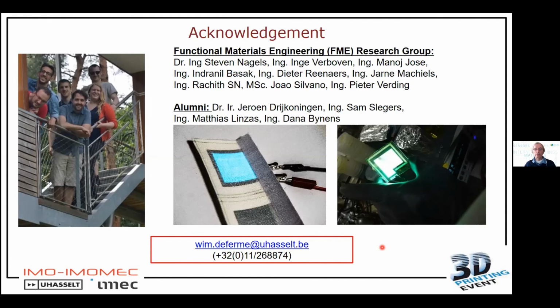Well, let's say that we have a few companies that have a lot of interest in this ultrasonic spray coating for roughness reduction and adding functionalities to 3D printed parts. But if you look at 3D printed parts, that is very difficult, because here I only show, let's say, a flat substrate which is 3D printed. If you start working with curves and holes inside the 3D part and so, then it becomes a bit more tricky. Then you have to play a bit more with ink formulation.